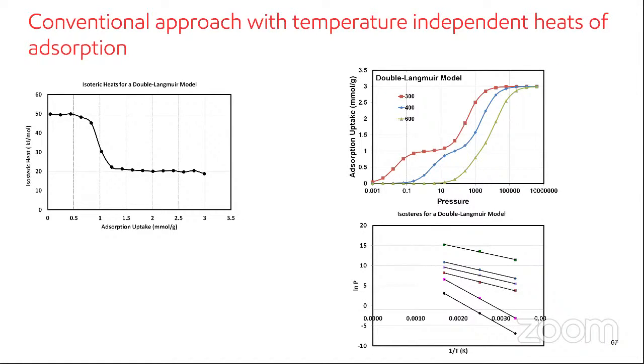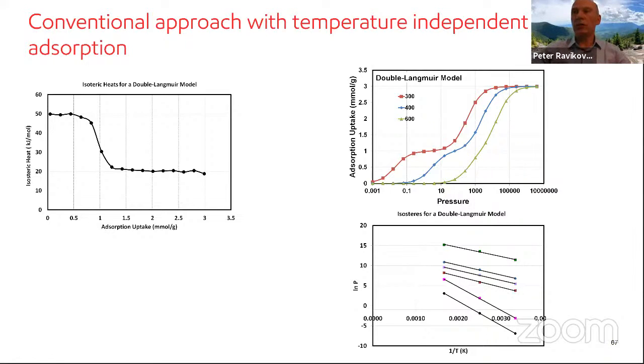Great. And we have one more from Zoom right now. This is from Andreas Seidel-Morgenstern. Thanks a lot, Peter. The heats of adsorption are measured and/or analyzed theoretically, typically for single component adsorption. Does this information allow a proper prediction of the heats of adsorption released if we have an adsorptive mixture? Well, if you know individual heats of adsorption and you can assume a certain adsorption theory, you can predict mixture behavior. So to the extent that you predict mixture behavior, you can estimate the mixture heats of adsorption.